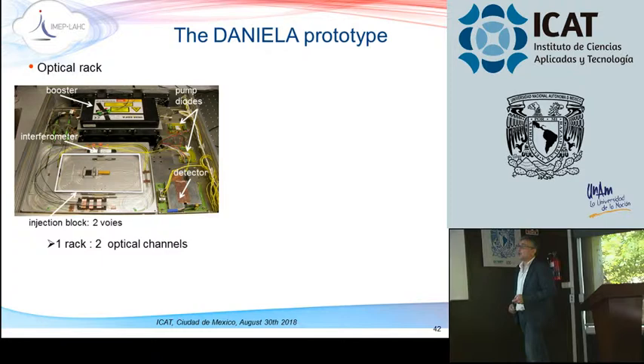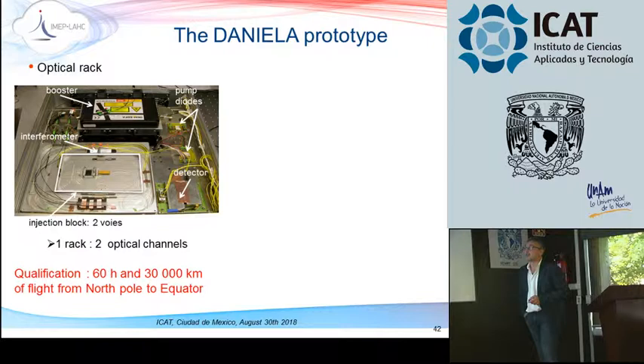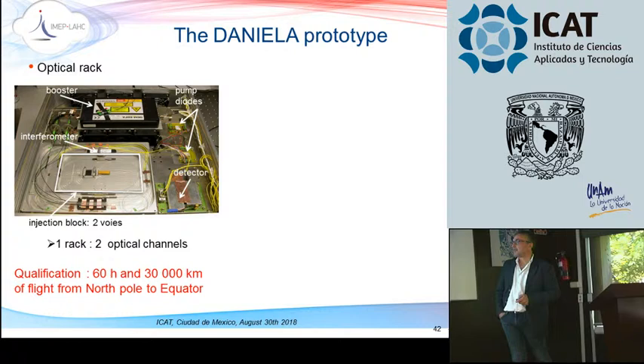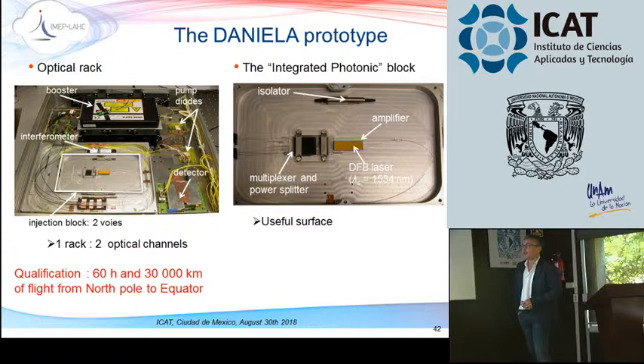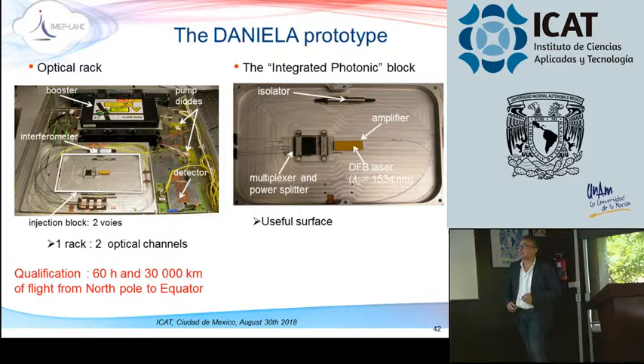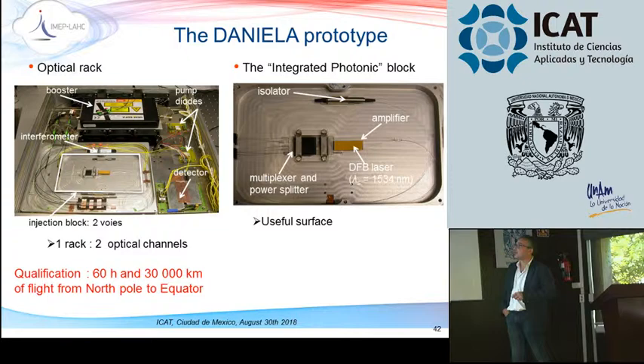With this, it was possible to integrate two optical channels. These two channels have been used on the plane, and they were qualified in flight during 60 hours and more than 30,000 kilometers, from the North Pole to the Equator. So it's a device that works really well. If you look at the optical part, the integrated photonic block, you see that it is quite empty.